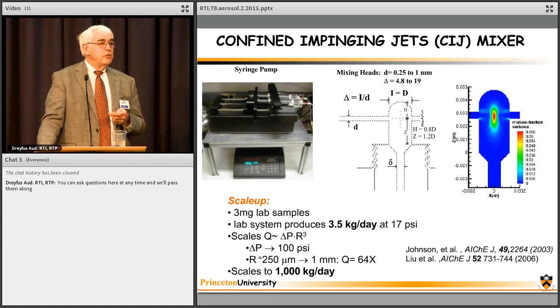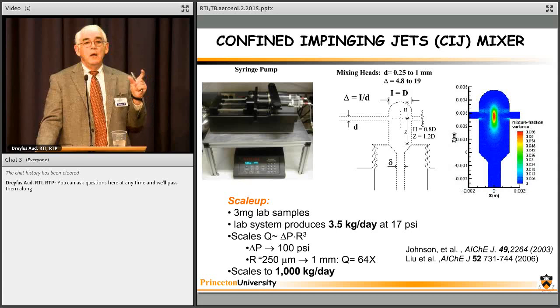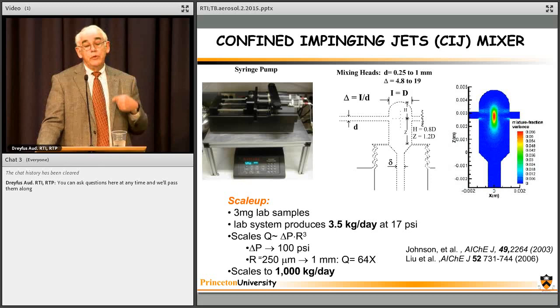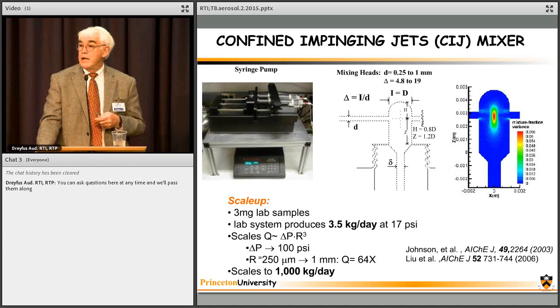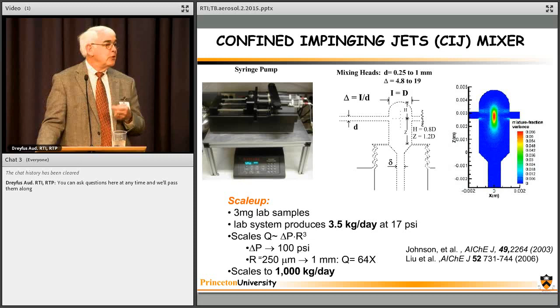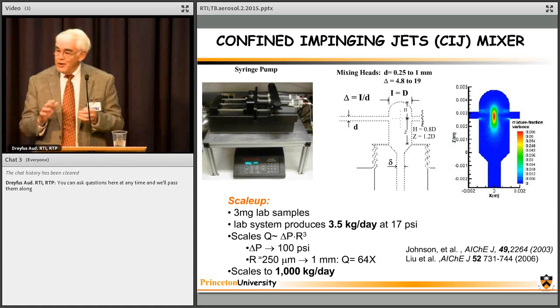And so BASF has a very large market, the largest market for carotenoids, is to take this beta-carotene, which has a log P of 9, very, very hydrophobic. It's so hydrophobic, if you have it as 1 or 10 micron crystals, not enough of it dissolves in the 4 hours through the salmon's gut to color the flesh red. So you have to put it down in 100 nanometer particles to make enough bioavailable to color the salmon's flesh. Okay? So in the supermarket, you're eating carrots, so it's also good. Beta-carotene is the color in carrots, so you're not doing anything bad for yourself.